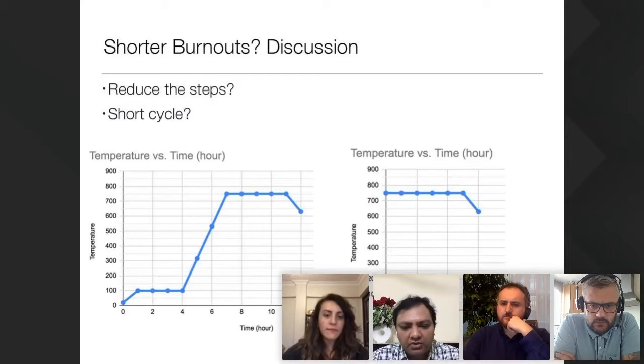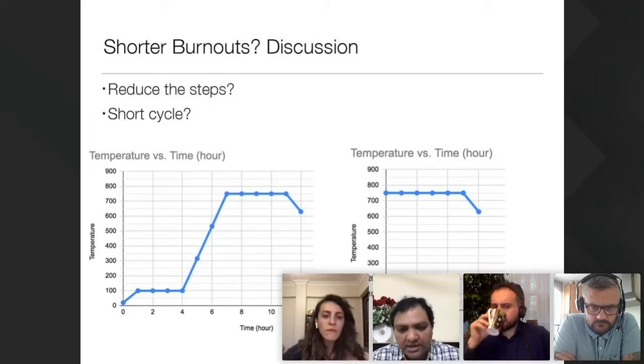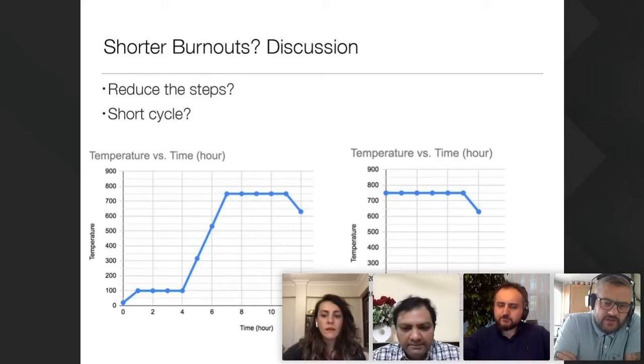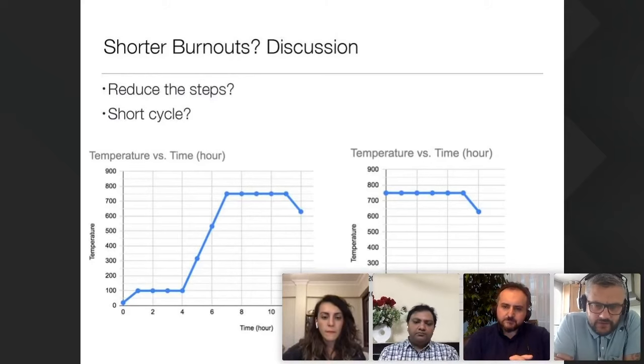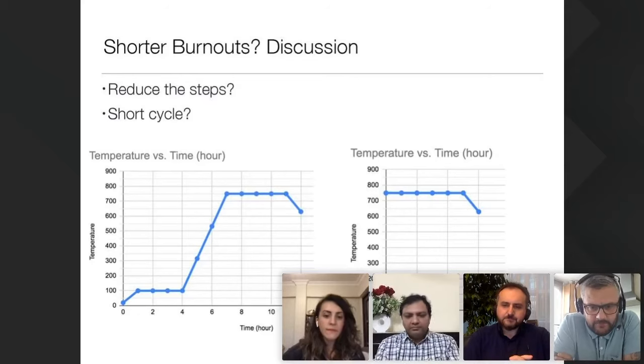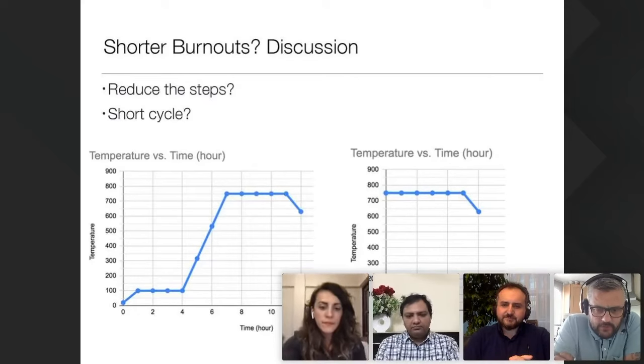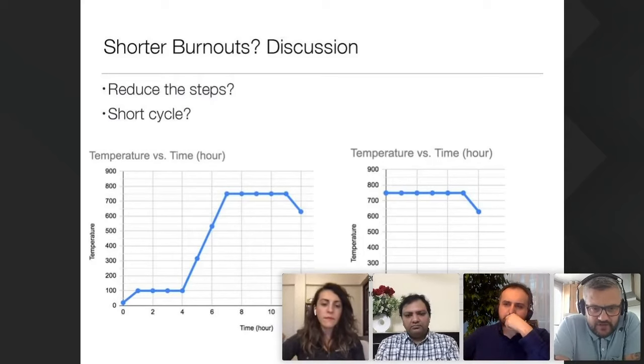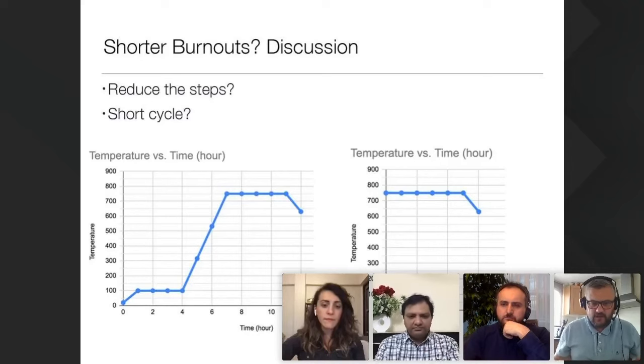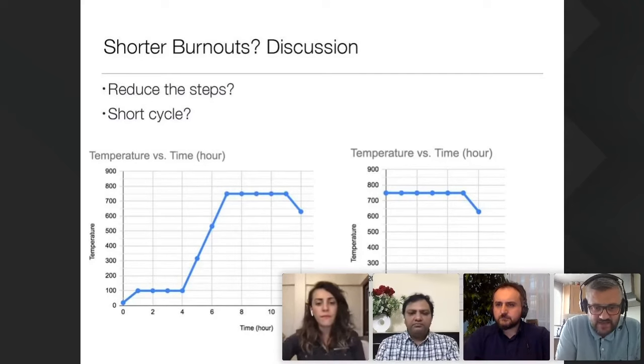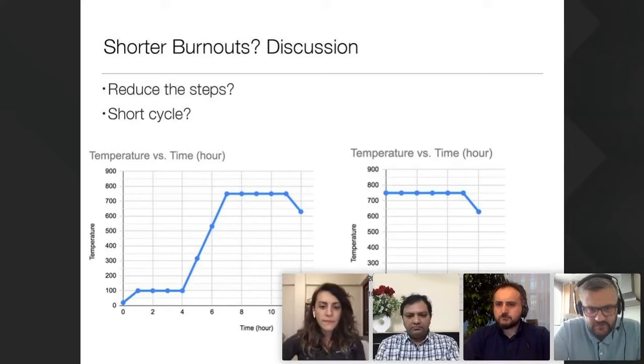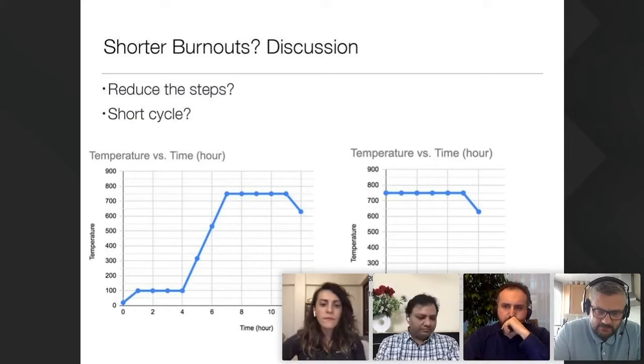Immediately when you take out from the furnace, you can go directly for the casting because you are sure that the flask is at the right temperature when the burnout is showing the precise temperature. The investment powder also holds heat very well on the inside. So one of the tests we do when creating a new recipe is take a flask out with a filigree item in it, and leave it for different times, 5, 10, 15 minutes before it goes into the casting machine. There's not a great deal of difference in the casting because the investment powder holds the heat very well.